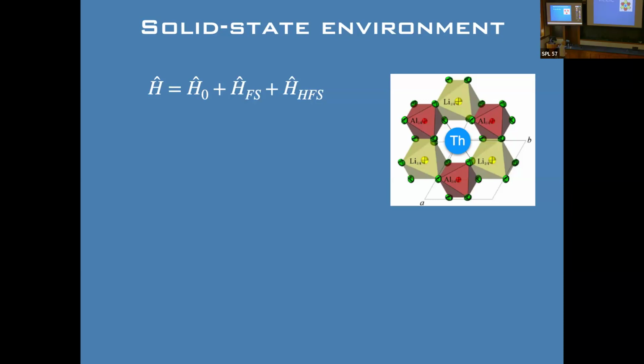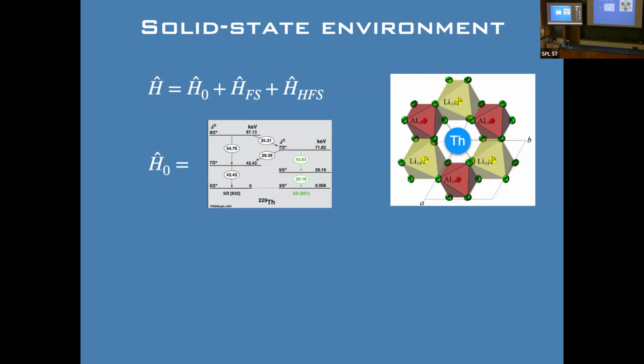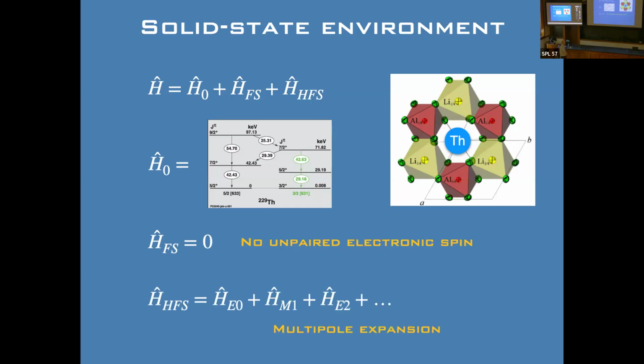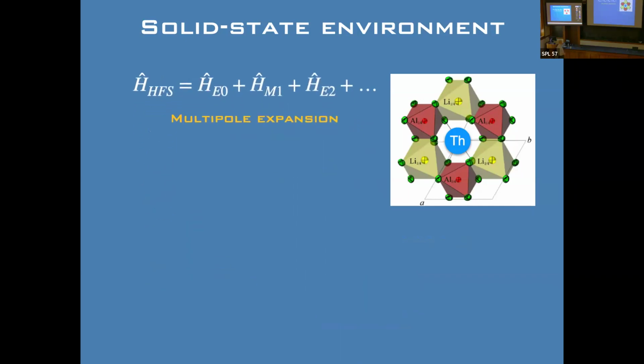And so if we look at the Hamiltonian of this, to first order it's still just these nuclear states that we can drive transitions toward. At the next level, if you do the right sort of crystal, with a high enough band gap so that you can get these VUV photons into the nucleus, you're pretty much always going to be working with ionic crystals. There's no unpaired electron spin, so there's really no fine structure effects. That leaves just a hyperfine interaction. This is basically the Hamiltonian of NMR or Mossbauer spectroscopy. You can just multipole expand it, and the terms are pretty simple.